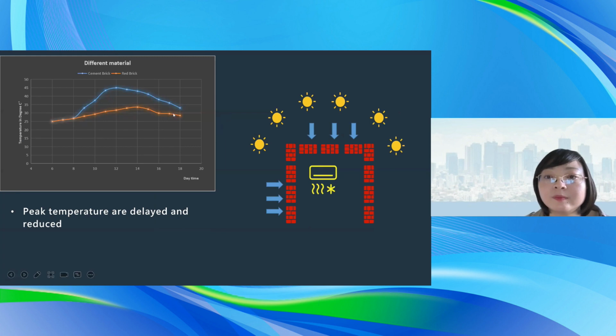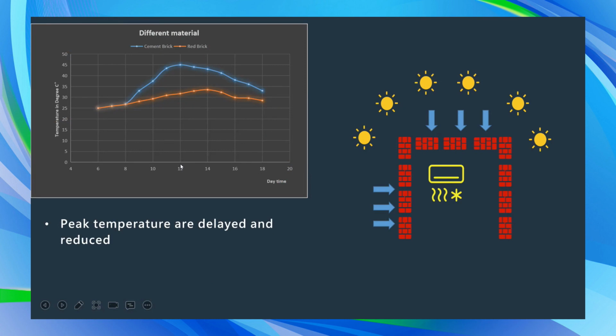If you can see the picture here, as I draw here, from morning 4 o'clock to evening 18 o'clock, with the sunrise to sunset, we really need very good insulation of the building material. The red curve represents the red bricks, while the blue curve represents the cement bricks. The peak temperature for the cement bricks is around 45 degrees C, which will be reached at 12 o'clock at noon. With the red bricks built up, the peak temperature is delayed and reduced to only 33 to 34 degrees.